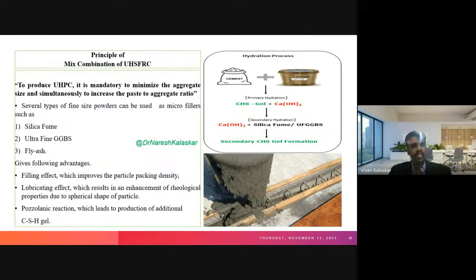The principles of mixed combination of UHPC, of course. In this UHPC, we are using cement as a binder. If you use more binder, we will face heat of hydration. So here we are replacing the binder with cementitious materials like silica fume, ultrafine GGBS, and fly ash. So these are the options. But in this total study, we have not used silica fume. We have taken only ultrafine GGBS and fly ash to reduce the cost of the mix.